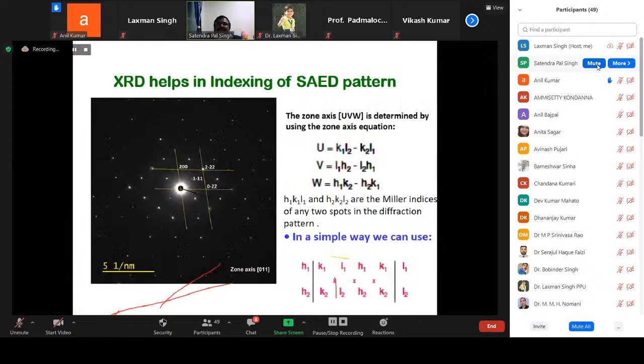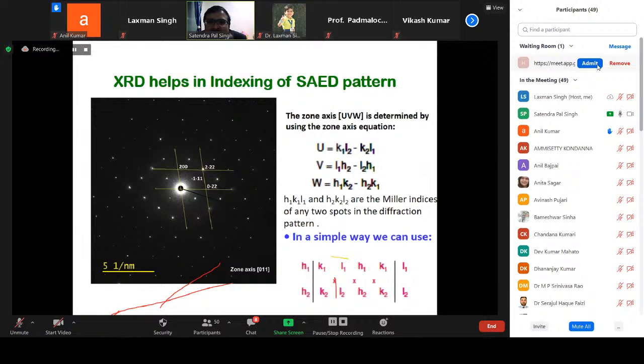Now, by knowing information like the indexing and obtaining a reliable refinement, we will be able to even index the TEM pattern. What do you call this? SAED pattern, that is the selected area electron diffraction pattern. This is a pattern of some different compound. I have indexed this pattern. Index means we have assigned the HKL values to each of these diffraction spots.